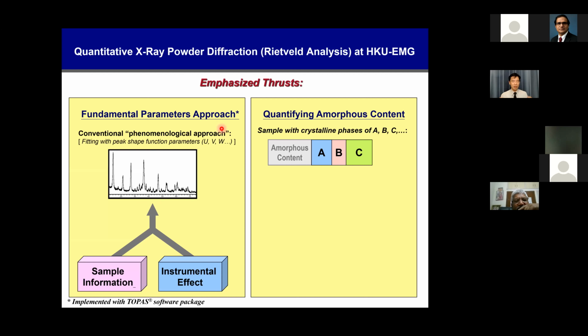One of the reasons is XRD by itself is a very instrument-specific technique, which means if I get a sample and put it on the instrument, the profile that you see will be a combination of both sample information and instrument effects. If you ever used the X-ray diffractometer, you understand there are so many different modules you have to set very carefully, together with different filters and different slits. So the instrument effect is huge in affecting your profile. Every profile is the combination of the two effects, which means if I measure the same sample on my machine and on your machine, you will get two different profiles. Or I should say, probably the 2 theta peak positions are still right, so qualitatively still right. But if you want to do quantitative calculation, that's not very reliable.